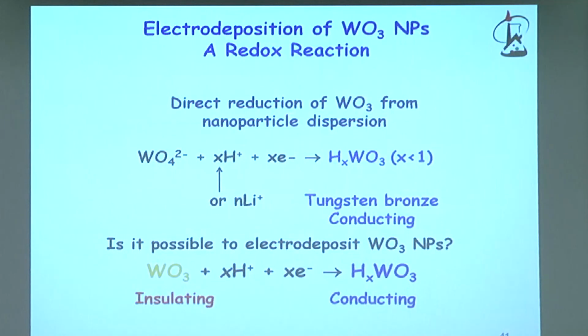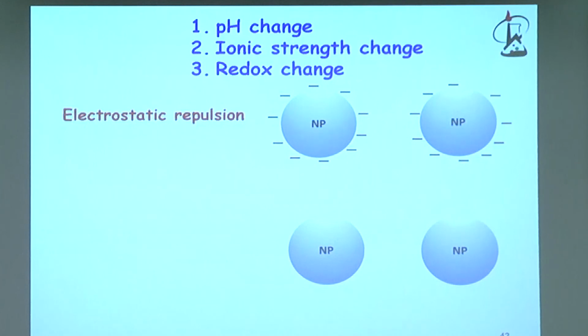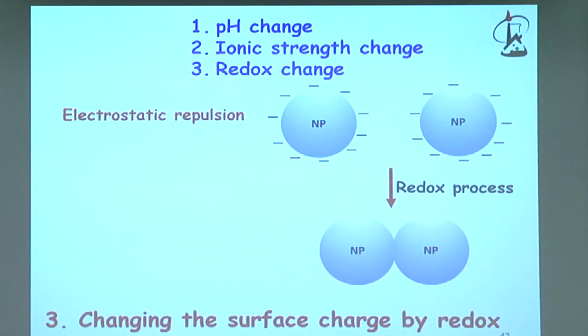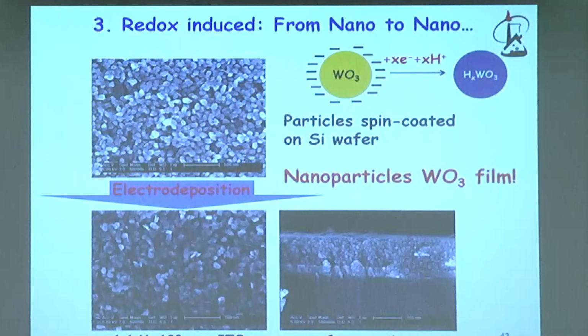So the tungsten oxide has a very nice property that upon reduction, okay, you change the redox state of the tungsten from tungsten 6 to tungsten 5 more or less, and by that you change the color from almost colorless to very strong blue, and this is indeed called tungsten bronze. And again, because what you can do here is you can simply reduce partially the negative charge of the nanoparticle, and then you can drive the deposition. And this is shown here very nicely.